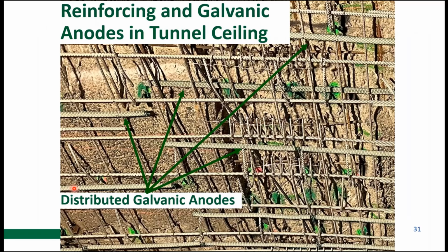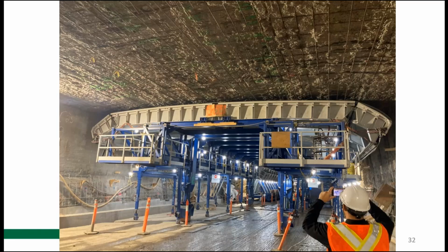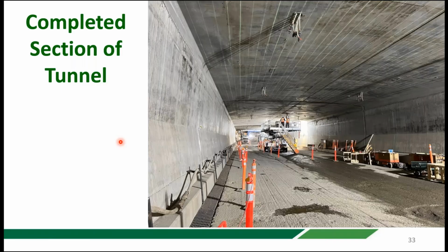And on the ceiling, they're doing basically the same thing. After the hydrodemolition, they're putting up new reinforcing steel and dowels. You can see the galvanic anodes installed here, one here, one here, one here, kind of essentially on a grid pattern. And for the ceiling work in the tunnel, they're doing basically the same thing as the walls. They have a 100-foot long section of forms that are automated and roll along inside the tunnel. And then they have these edges that the whole thing can be set with hydraulic cylinders, and the edges can push up to seal on the edges. And they basically pump those repairs as well. And then obviously they just keep moving along down the tunnel, 100-foot section at a time.